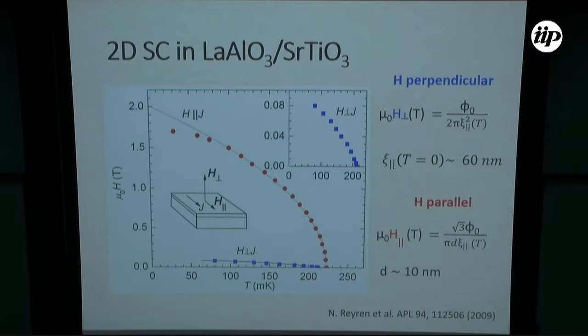So here are the measurements of the critical field for the perpendicular configuration. So magnetic field applied perpendicular to the interface, where the critical field is around 100 millitesla, and from that we can extract an in-plane coherence length of 60 nanometer, whereas when we apply the magnetic field in the plane of the interface, we see that the critical field reaches 1.5 Tesla, and also has a square root behavior in temperature, as is expected for a 2D system. And from this Tinkham formula, we can extract an average or an effective thickness of the superconducting gas that is 10 nanometer.